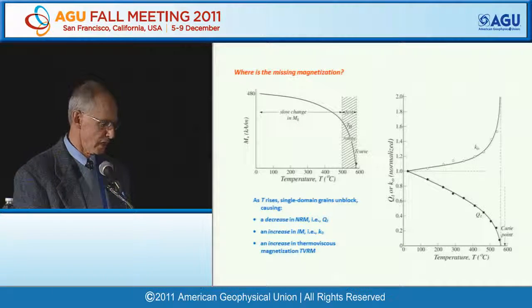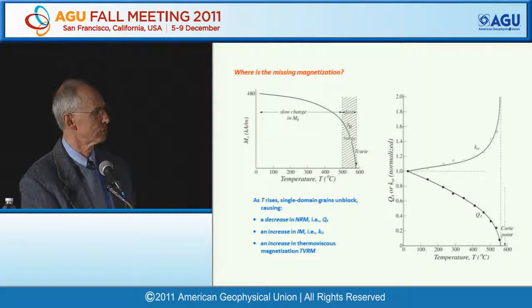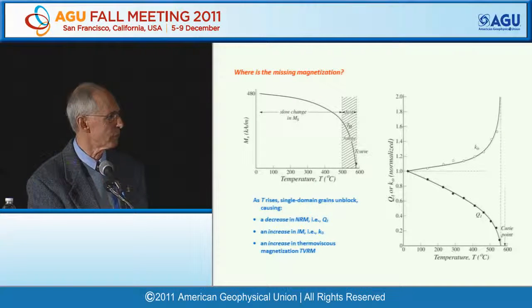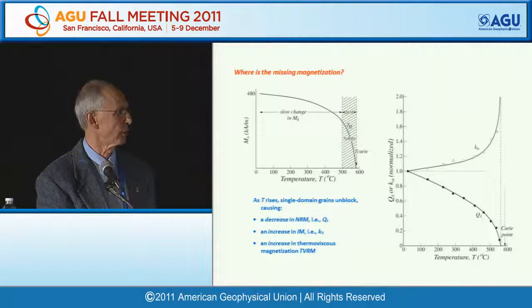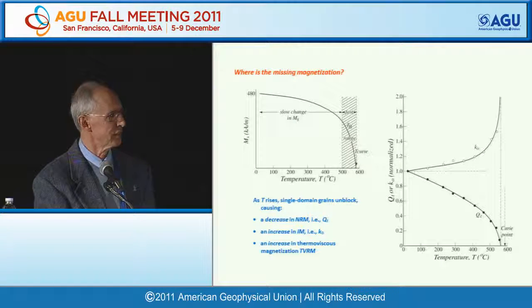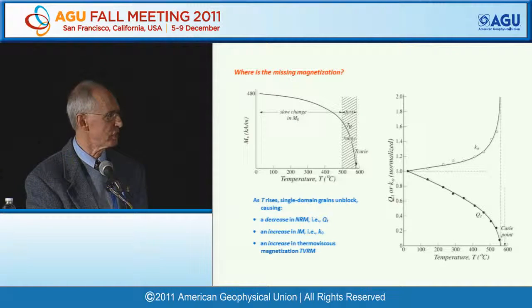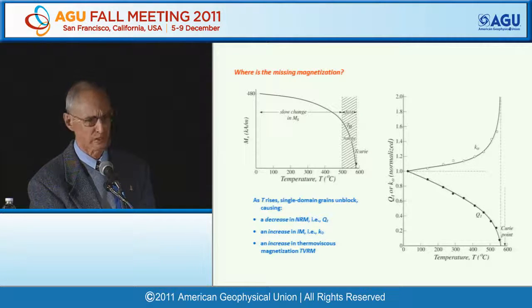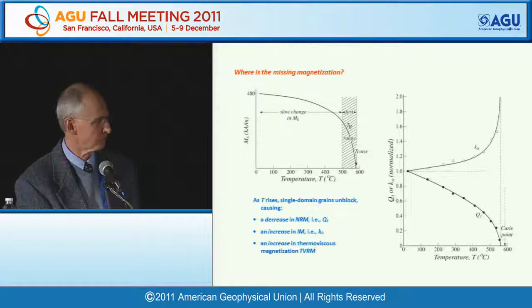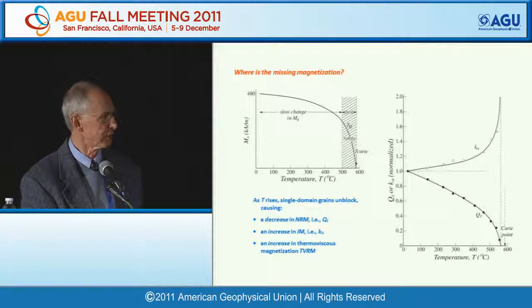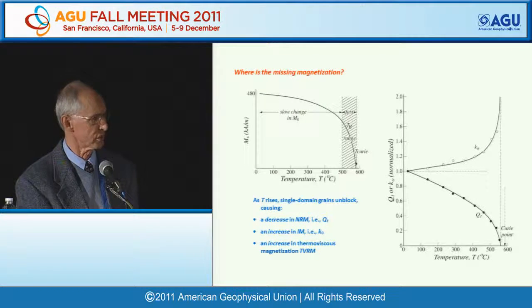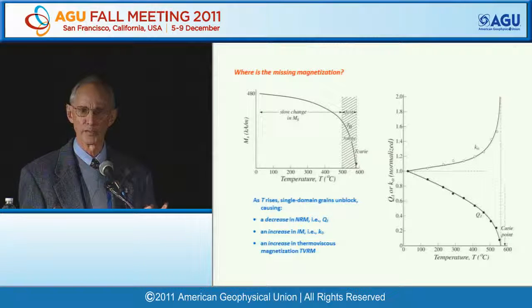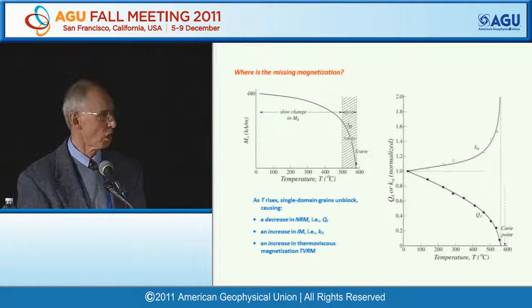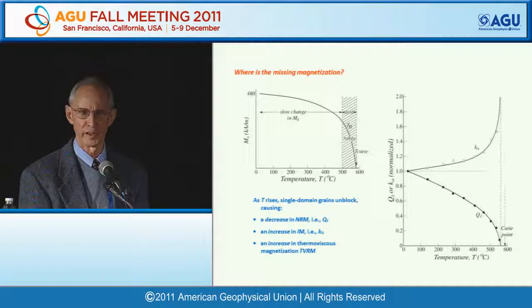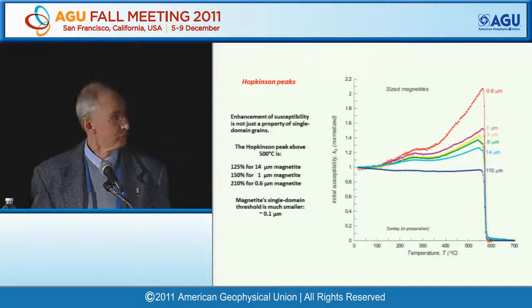Well, part of it may actually be due to the physics of the situation. When the temperature rises, single domain grains unblock, therefore the Q goes down, the NRM contribution goes down, but the induced magnetization, the initial susceptibility, goes up. Another effect is that the thermoviscous magnetization, what you get by simply applying the field for a very long time, also goes up, and that's another effect that may also be very important.